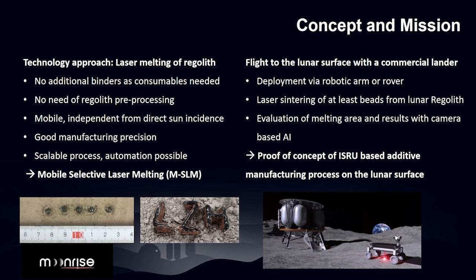As we have developed this technology for several years, we are now at the point where we start development of the flight hardware of the experiment, and we plan to deliver it with a commercial lander to the lunar surface, deployed via a robotic arm or a rover, and then start sintering tests on the surface, at least laser beads, but hopefully two-dimensional objects on the lunar surface. Afterwards, we will make an evaluation of the melting results with a camera-based artificial intelligence.